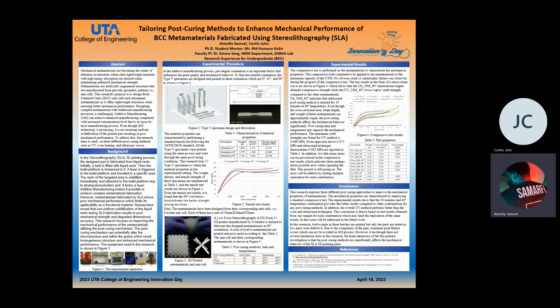In the additive manufacturing process, part orientation is an important factor that improves the print quality and the mechanical strength of the part. To find a suitable orientation, we have the type V specimen that we designed, printed, and tested in three orientations, which are 0 degrees, 45 degrees, and 90 degrees. They're all shown in the figure below, Figure 2.